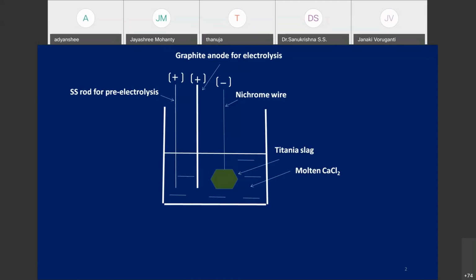When the potential is like this, oxygen ionization from the slag material takes place. Oxygen comes out from the slag material and reacts with the carbon anode to produce CO or CO2. The slag originally contains iron oxide, some iron metal, and the oxides of titanium. Besides, some impurities are also there.